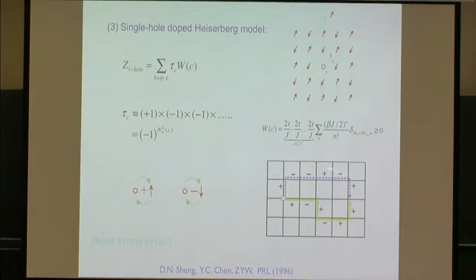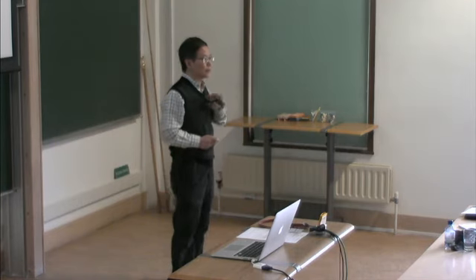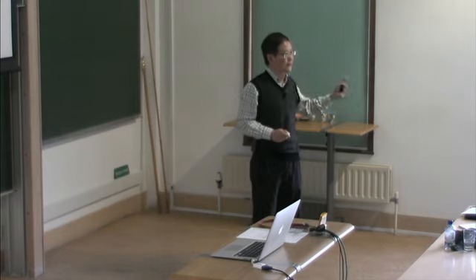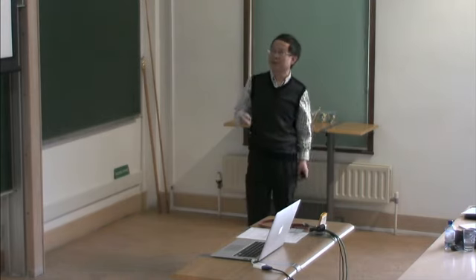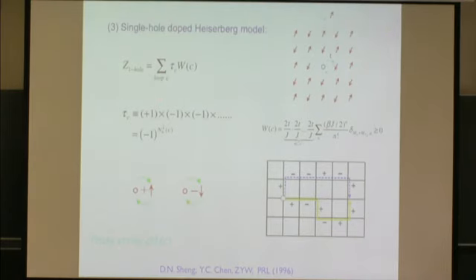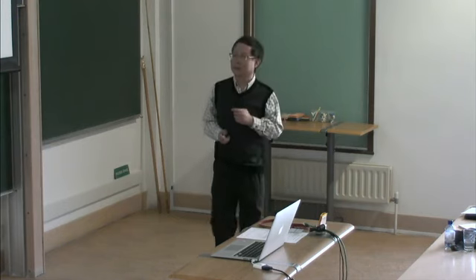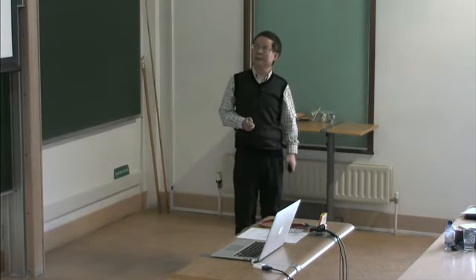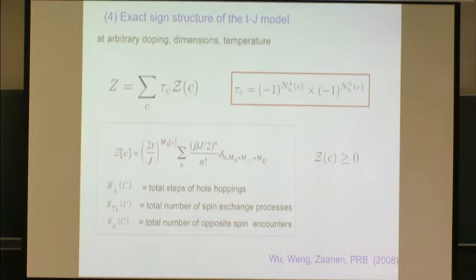So when the hole completes the path, you have this product of signs. This sign has nothing to do with the fermion sign. It originates from there, but it's quite different. And this is something again to do with strong coupling. Later on, it was found that this sign structure holds for the t-J model for arbitrary doping, arbitrary dimension and temperature, as long as it's a bipartite lattice.